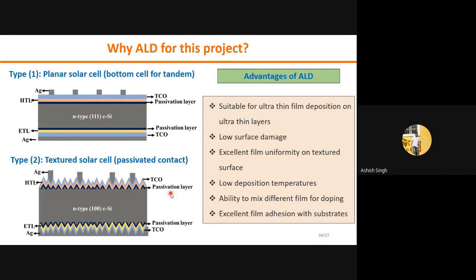And the film thickness should be ultra thin, like 1 nanometer or 2 nanometer thick films that we need to deposit. Other techniques cannot do such conformal deposition, and this is the advantage of ALD. It is suitable for ultra thin film deposition. Since we are using a remote plasma ALD system, surface damage will be very low, and thermal ALD doesn't do any surface damage. All the layers in the device are not more than 200 nanometers. Suppose you put a passivation layer, and after that we need to put a hole transport layer. If we put it by sputtering, the passivation layer may be damaged because of the sputtering energy, the plasma energy. That's why we are using the remote ALD system.